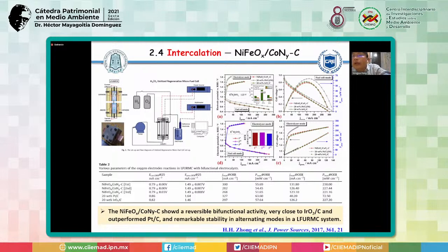But this one we worked on at the University of Poitiers, in collaboration with Professor Alonso Wang. So here we show the electrocatalyst compared with the platinum. It shows very nice bifunctional activity. It's very close to iridium oxide and outperforms platinum carbon. So we get very nice stability in alternative modes using that regenerative micro fuel cell. So we ran three cycles, and it is almost stable. This one is already published in the journal.